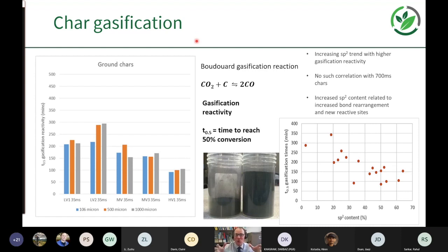And we've looked at the gasification reactivity of these partially burnt chars, because for these partially burnt chars, there'll be insufficient oxygen to combust them further in the furnace, so they have to react by the Boudouard gasification reaction to generate more carbon monoxide. And then this picture illustrates the difference in the char volume. This is the same mass of material, the same mass of coal and char. So the char can occupy a larger volume, and that has implications on the efficient utilization.